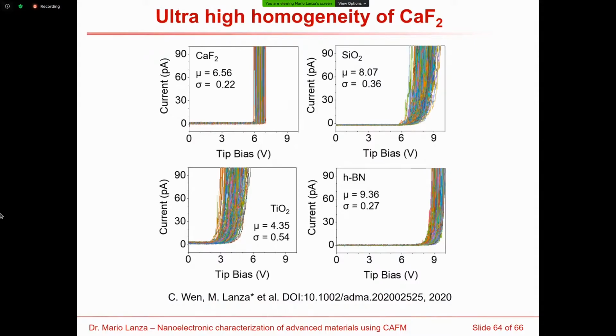And what you can see, if you perform hundreds of IV curves at different locations of each sample, is that the calcium fluoride shows the lowest deviation of the IV curves, which indicates that it is the most homogeneous material of all of them. Here we are seeing that the boron nitride is also somehow homogeneous, but this boron nitride is fabricated by mechanical exfoliation. If you repeat the experiment in CVD grown boron nitride, you will see a much wider deviation. So the boron nitride in this case cannot be really considered as a dielectric for wafer scale integration because this method is not scalable. So comparing the calcium fluoride with silicon oxide and with titanium oxide, we observe outstanding results.